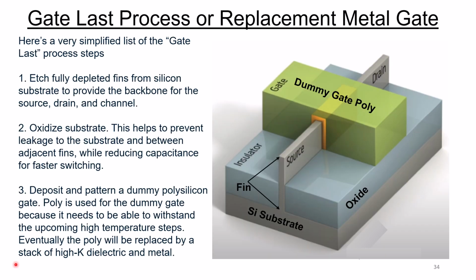Here's a very simplified list of the gate last process steps. First, we fully etch the depleted fins from the silicon substrate to provide the backbone for the source, drain, and channel. And I think we've talked about this in great detail already. The next step is we oxidize the substrate, and that's this gray region here. And this helps to prevent the leakage to the substrate and between adjacent fins while reducing capacitance for faster switching. And I think we've probably mentioned that before also.